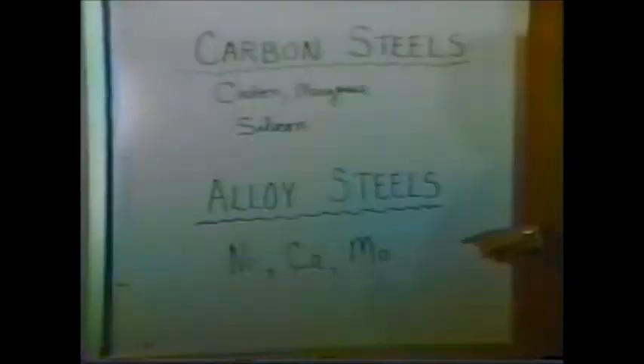Now, these elements are expensive, and if you can get away without using them, if you need, for example, only to machine the steel, or you do not need a specific strength level that is achievable with heat treating, you can get away without these. But there are customers who do need to have a response to heat treatment, and they will specify levels of nickel, chromium, and molybdenum in their alloy steels.